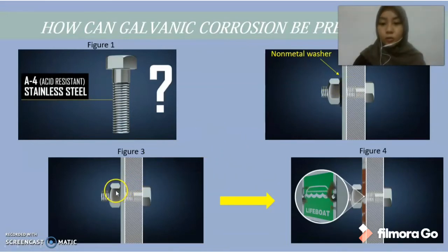If there is no washer, then the aluminium may act as the anode and corrode around the bolt, and then it becomes like this. The connection will then be weakened in the event of additional external stresses such as wind. In this case, the sign may work loose and fall down while the bolt is left behind. We must remember that a weakness of the isolating washer may be that the screws or bolts lose their pretension.